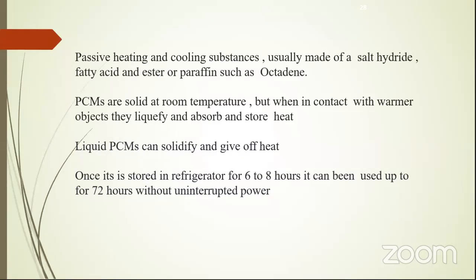And liquid PCMs can solidify and give off heat. Once it is stored in a refrigerator for 6 to 8 hours, it can be used for up to 72 hours without uninterrupted power. That is the reason why we are using it, as I already said, for transportation of medications. For life-saving medications, we use these phase change materials to maintain a constant temperature. If you use a proper refrigerator with this kind of PCM materials, for 72 hours without any power we can have a normal temperature. We can maintain the temperature in the baby's beds. So that's why we are going for this kind of PCM materials.